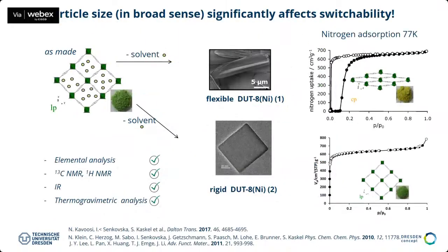Basically by particle size. So these are just different particle sizes. Here we have the closed pore form in the beginning, and then when we have the gas uptake, we go to the open pore form, and then in the desorption, here we still have the open pore form, and then here we close. And this hysteresis you only observe for large crystals. If you synthesize your material as very small nanoparticles, then after the solvent removal, your material stays in the open pore form, while for the large crystals, you go to the contracted pore form.